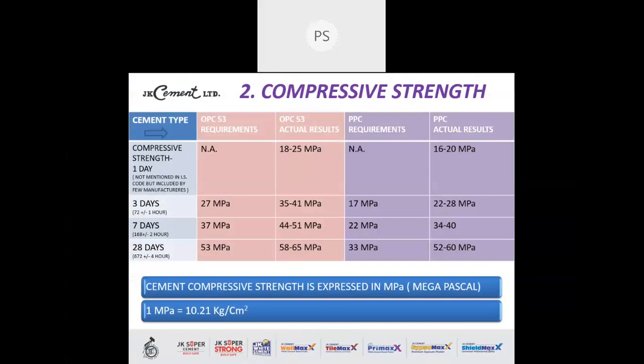Now we look at the PPC requirements. Again, 1 day strength is not available as per IS codal provisions. We get a strength of 16 to 20 MPa in Indian cement conditions. 3 day strength minimum requirement is 17 MPa. We get a strength of 22 to 28 MPa. 7 day should be 22 MPa minimum. We get 34 to 40 MPa. And 28 day, it should be minimum 33 MPa. We get a strength range of almost double, 52 to 60 MPa.